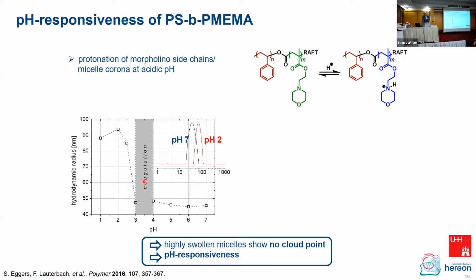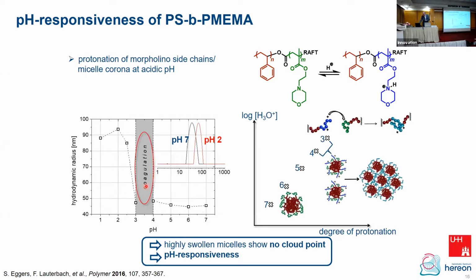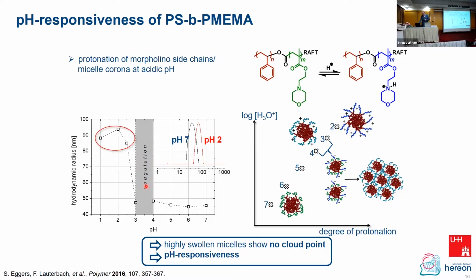Now, when you decrease the pH, at some point it's getting protonated, it becomes a polyelectrolyte and expands. And due to that, you get an increase in the hydrodynamic radius, and you have a coagulation part here in the gray area, which is funny, and we don't know exactly what happens there. My feeling is, but I may be wrong, that we have aggregation, or coagulation and precipitation, because we have unequal distribution of maybe protonation. Different chains are differently strongly protonated, and we get some segregation between two dissimilar sorts of chains. But this is something we don't really know. It's speculation.